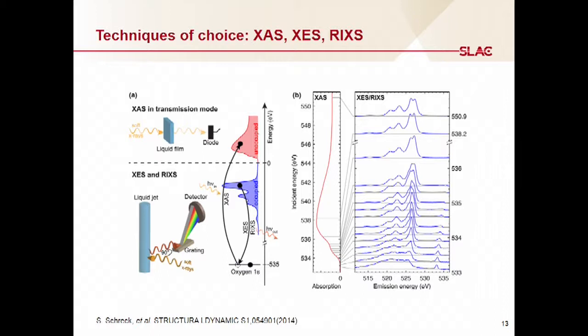Well, they're really kind of summarized by X-ray absorption spectroscopy, X-ray emission spectroscopy, and resonant inelastic X-ray scattering. They're all really linked together. If you have a sample, and this can be really any atomic species from the periodic table, you know that they are characterized by these very unique atomic levels that the electrons are sitting at. So if we come in with the X-rays of well-defined energy, we can promote an electron into an unoccupied state. That's the process of absorption.